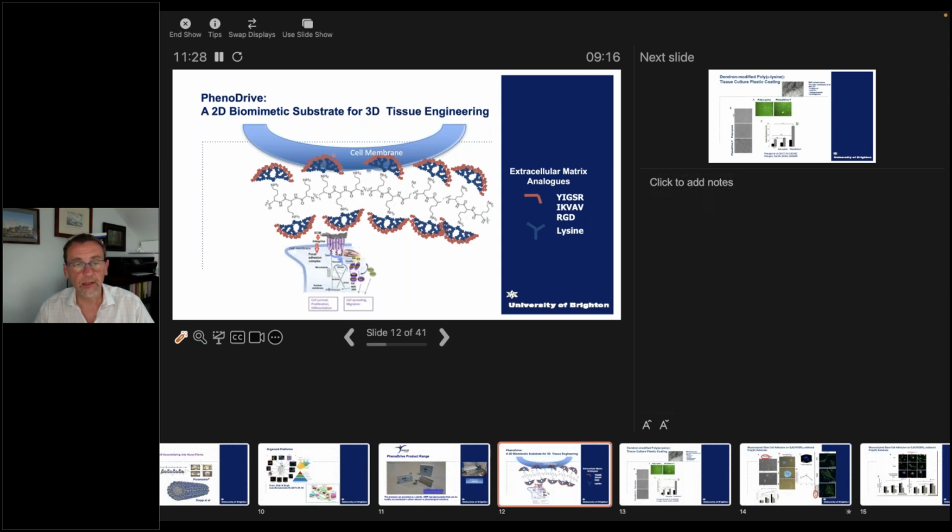Imagine a nanotree where the root of the tree is covalently bound, grafted, to the linear polymer, and the uppermost branching generation are those red rods that you have seen in the previous slides, which can present to the cell membrane and indeed to the cell receptors those bioligands in a very controlled manner, both in terms of density, depending on the number of branches, and in terms of spacing, again depending on the number of branches.